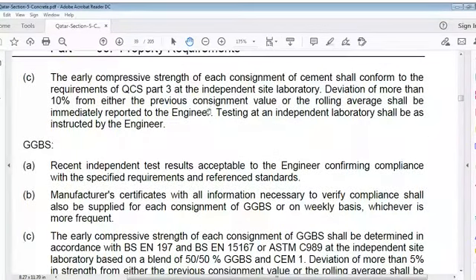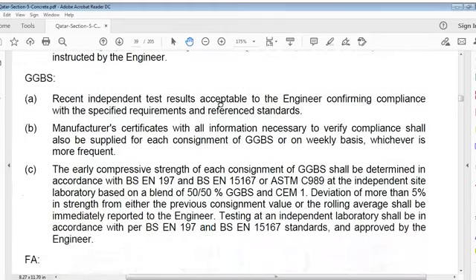Early compressive strength of each consignment of cement shall conform to requirements of QCS Part 3 at independent site laboratory. Deviation of more than 10% from either previous consignment value or rolling average shall be immediately reported to engineer. Testing at an independent laboratory shall be as instructed by engineer.